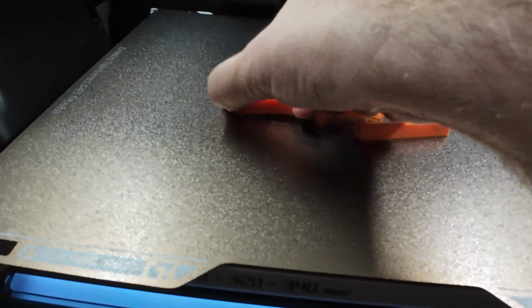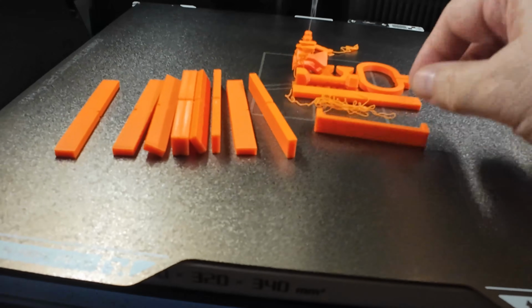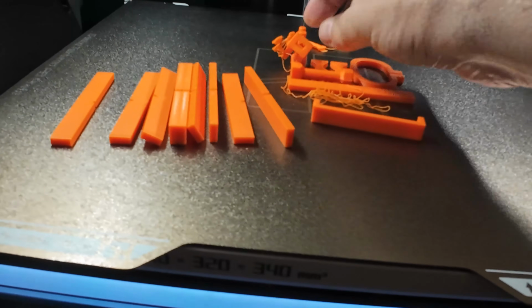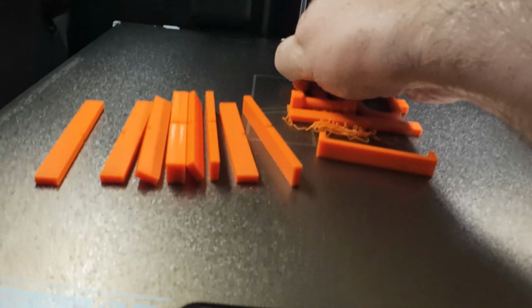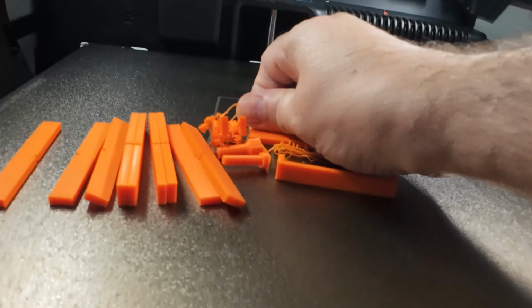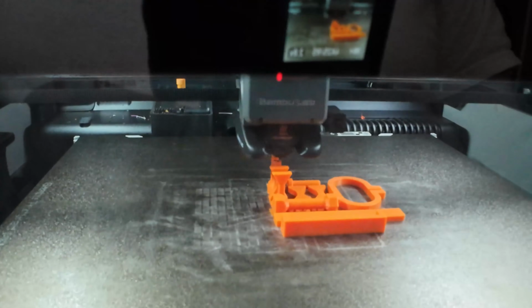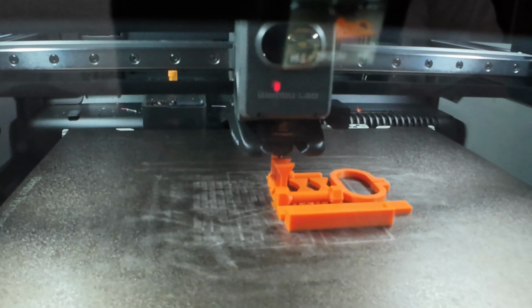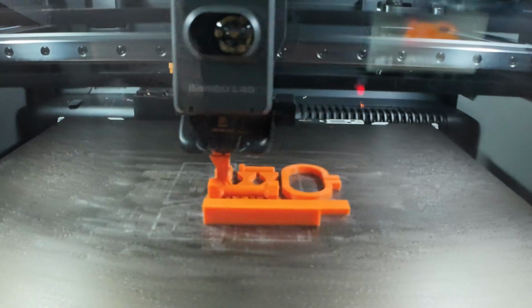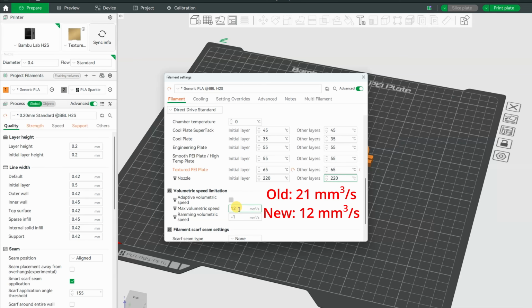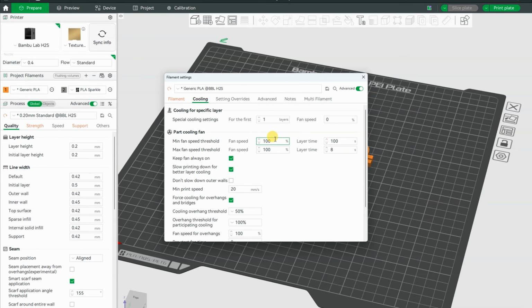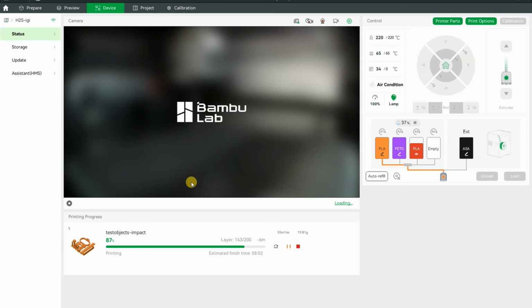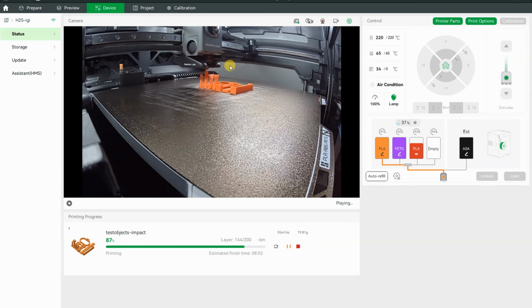For the infill it is okay, but from PLA I'm expecting a little bit better adhesion. I made a few changes in the slicer and added some glue on the build surface, and I'm reprinting the main test objects, without those for the impact test, and this time it was completely fine. Here you can see my changes. Generic PLA, which is slower printing, and the minimum part cooling fan is also 100%. And this is a picture from the camera. This is the last test subject, so it was completely fine printing this time.